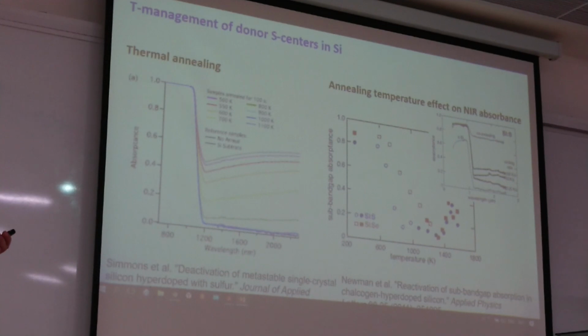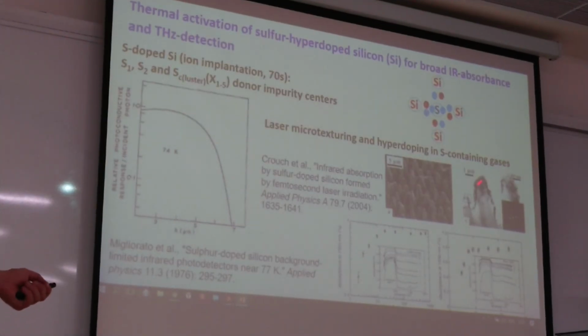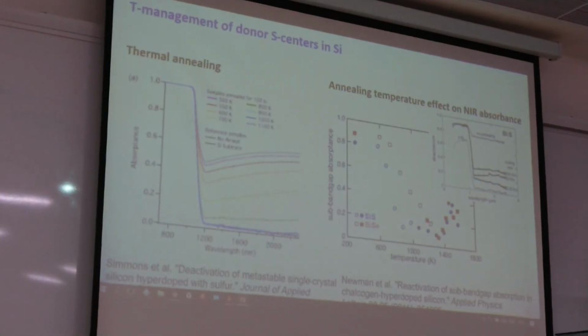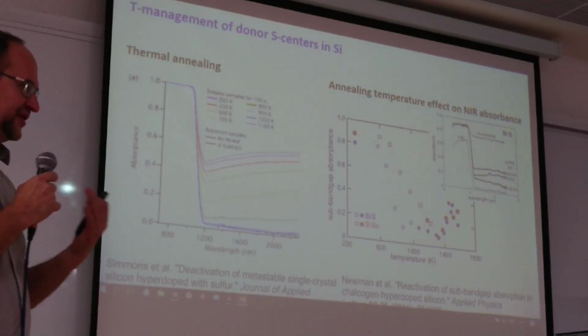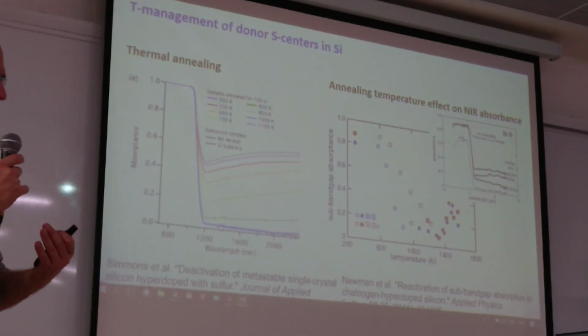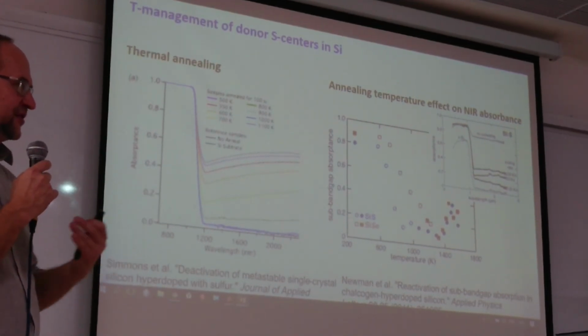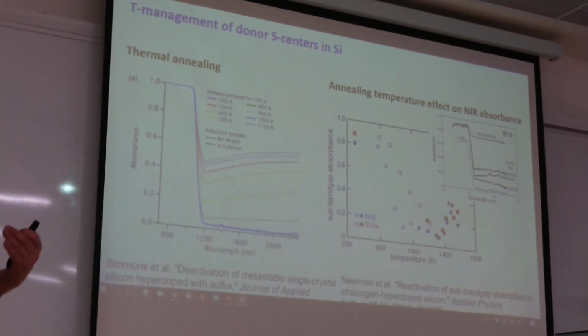Actually, the produced structures look very defective. Like here, this is a cross-sectional analysis by electron microscopy, and there is a necessity to make thermal annealing, so make thermal management of donor sulfur centers. Because after laser irradiation, the crystalline lattice is somewhat distorted, and electrical conductivity is very poor. So through thermal annealing, we can restore the lattice, but simultaneously people observe that annealing makes the donor effect in infrared absorption much lower.